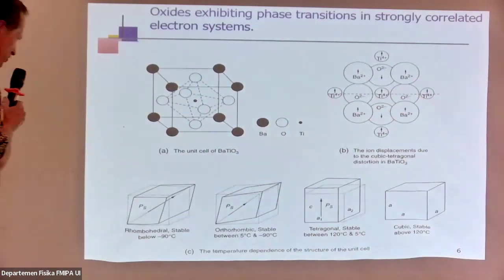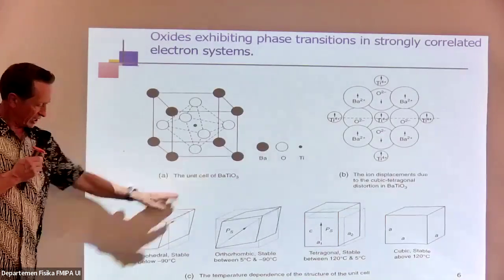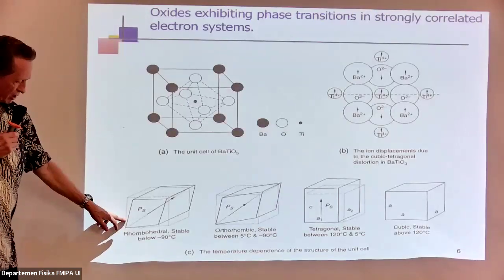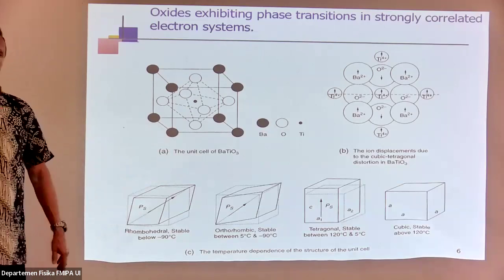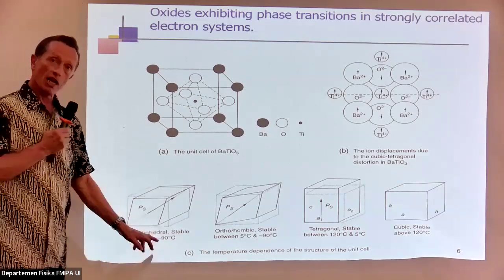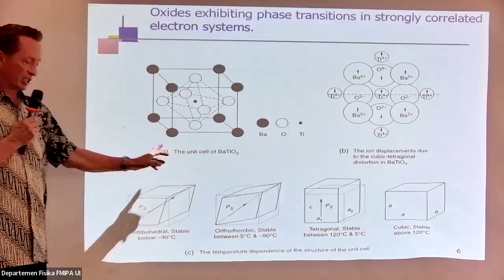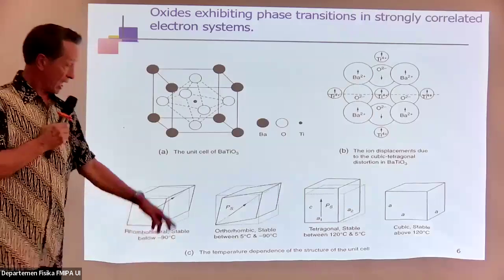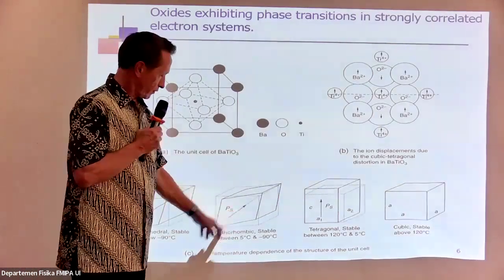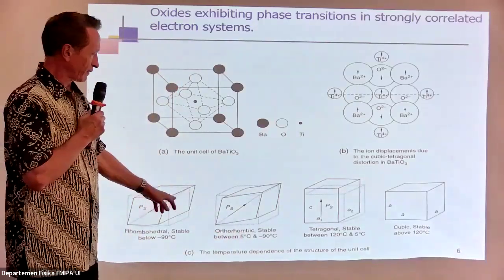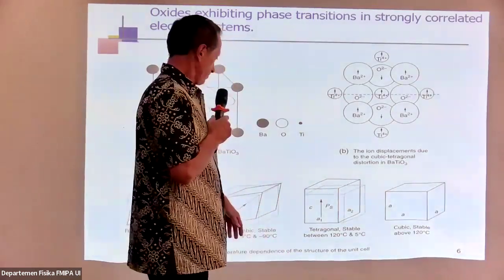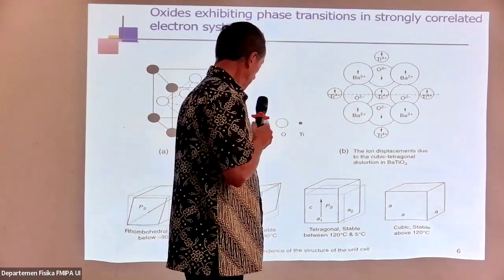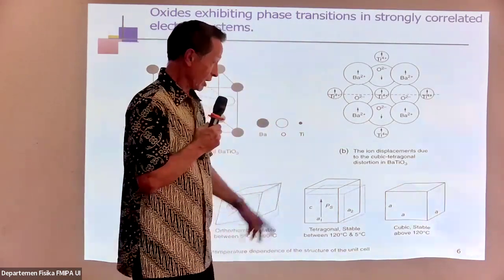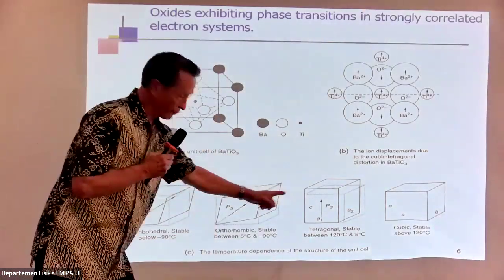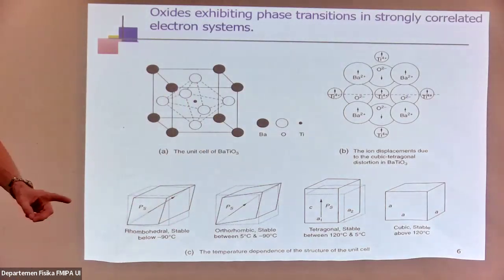So here, on the right part, you have the different polarities of all the atoms you can find in the structure. And after that, in the case of barium titanate, you have the different phases you can encounter when you study the material in a large temperature range. So at very low temperature, barium titanate is in the rhombohedral structure. And above that, it goes through another phase, which is the orthorhombic phase. After that, above the temperature related to the orthorhombic state, the material comes into the tetragonal structure. And you see the difference. All these three phases are ferroelectric phases.